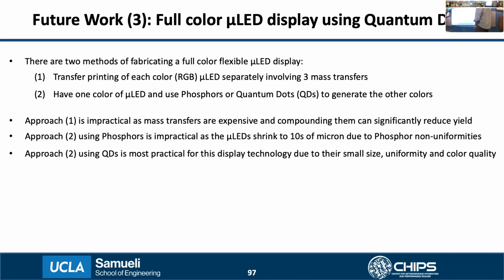So approach 1 using the 3 mass transfer steps is expensive because mass transfers are usually expensive and also typically a low yield process, and hence compounding them can significantly reduce the overall yield. Approach 2 using phosphors is also difficult because when the micro LEDs shrink down to tens of micron size, there's significant non-uniformity issues because the phosphors themselves have particles that are in the tens of micron size.